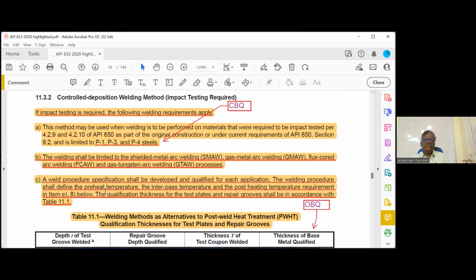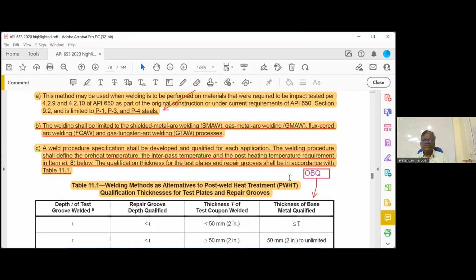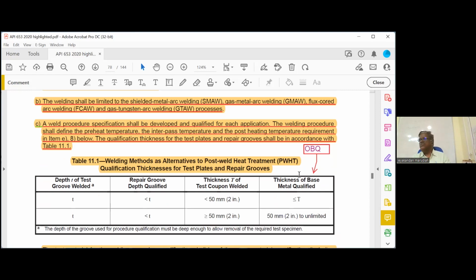The weld procedure shall define preheat, interpass, all. So this is the table you have to follow. This is an open book question. You remember I told you, in Section 9, generally 2T is allowed. Here, for example, if the thickness of the test coupon is less than 2 inch, only less than that thickness is allowed. When the thickness of the test coupon is greater than 2 inch, it is unlimited. If you take deposited weld metal, small t, whatever thickness you are welding, only less than that thickness is allowed.